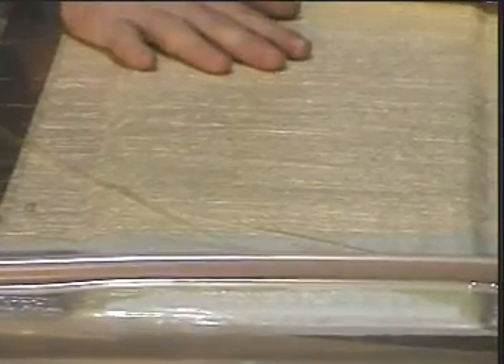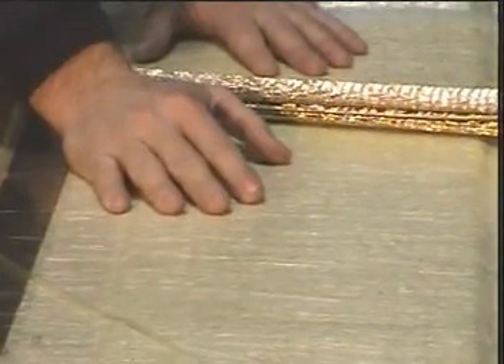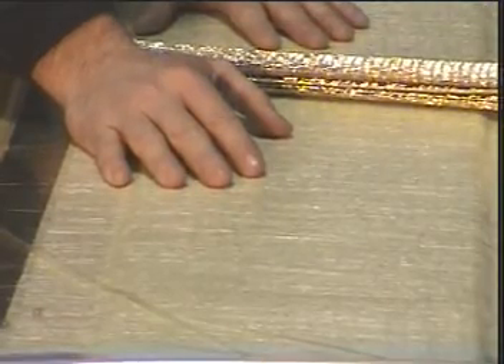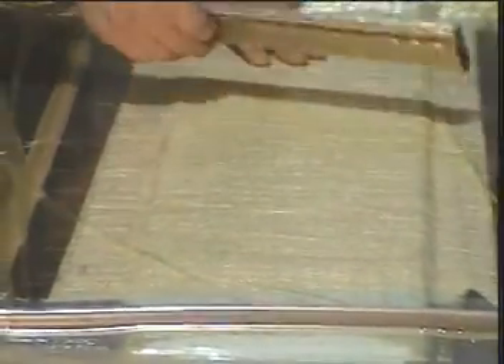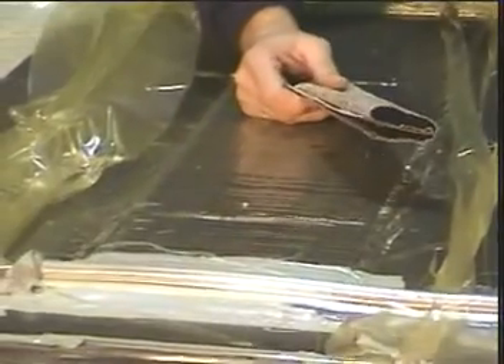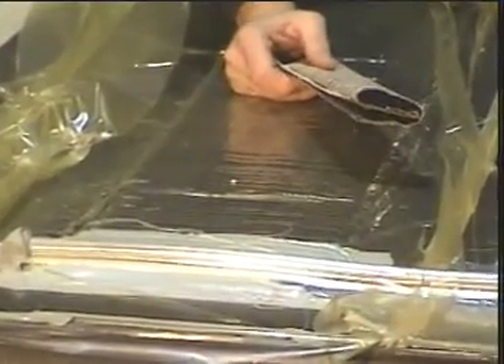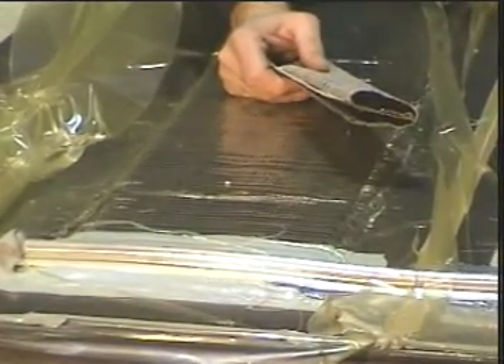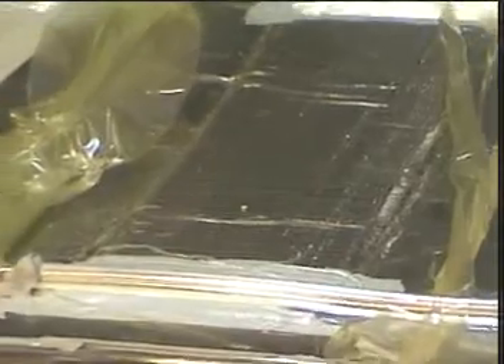And just to make sure you realize, this tool is actually heated. This tool's up around 100 degrees, so we should get as good a flow as you can get. You notice that the carbon laminate, we haven't even been able to get any resin into it. Carbon under vacuum is extremely difficult to infuse. And meanwhile, you can see that the Hardwire laminates are beginning to fill pretty aggressively from the inside out. This is where the laminate itself acts as the distribution media. Just going to let you watch this process for a bit.